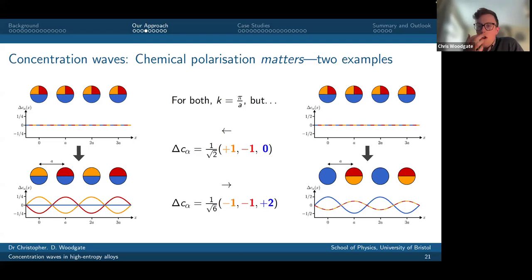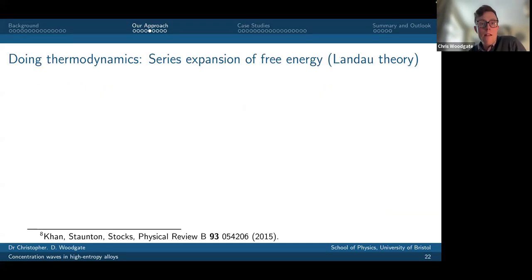And on the right, instead of the blue atoms remaining disordered and the orange and red atoms alternating, I'm describing a situation where the ordering is emerging between the blue atoms and the orange and red atoms, with the orange and red atoms being unaffected. And there the concentration wave has a different chemical polarization, -1, -1, +2. That's going to be important in what I talk about in a little bit, because the chemical polarization tells me about how the different chemical species are partitioning themselves onto different lattice sites.